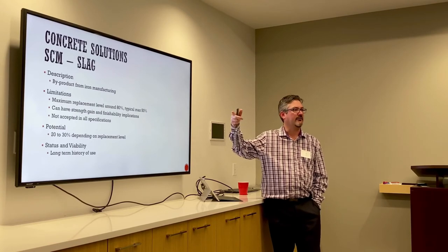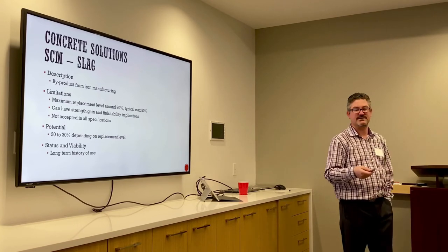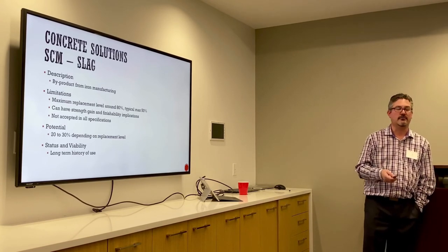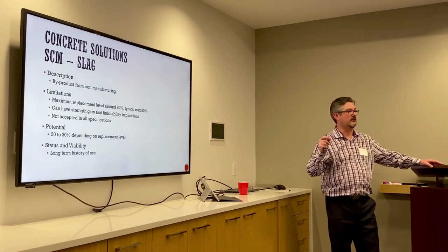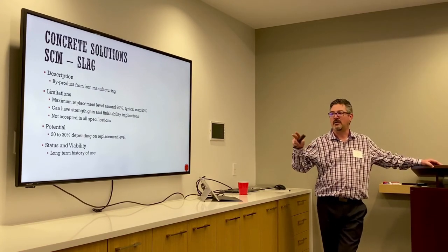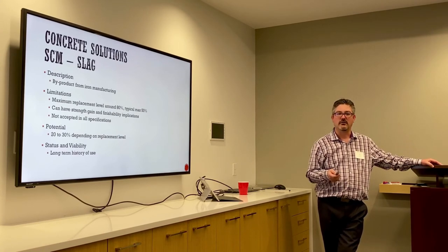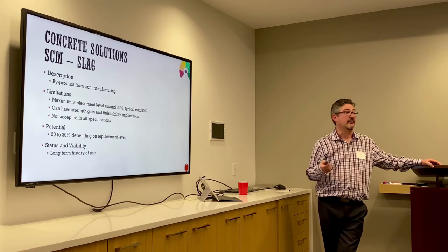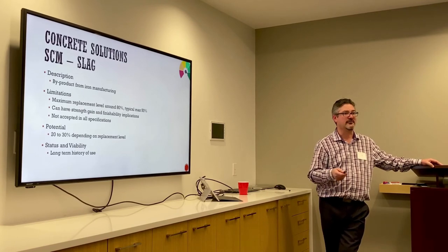Again, it can have strength implications, finishability implications, project schedules and things like that. Not accepted in all specifications, but has the potential for reducing the CO2, the embodied carbon, for concrete by between 20 and 30%, depending on how much you use. Again, long-term history of use, so I rate this at a 6. So something that can be done today, not really a lot of thought involved in doing this.